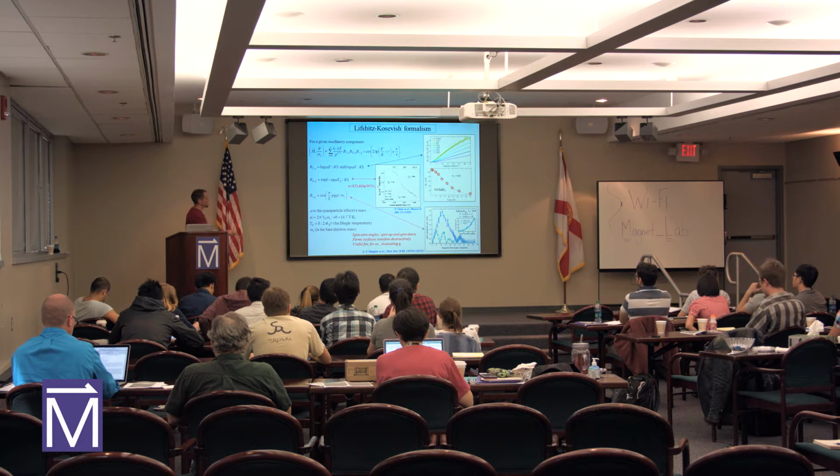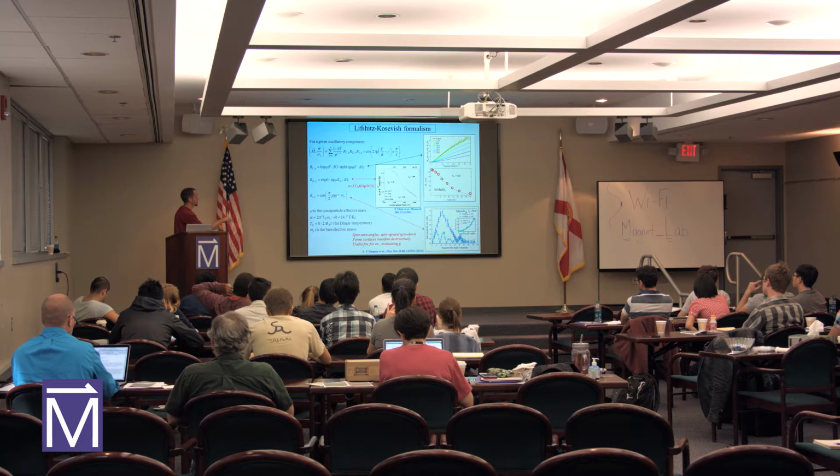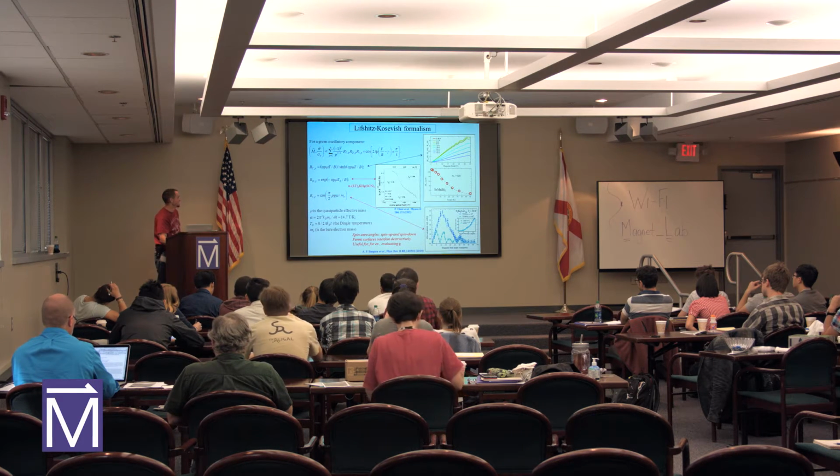Okay, if you do a very careful analysis of angle dependence, you can actually go backwards and find the g factor for the material, which for electrons is usually close to 2. Okay, so this is the information we can extract once we've actually collected some quantum oscillation data.